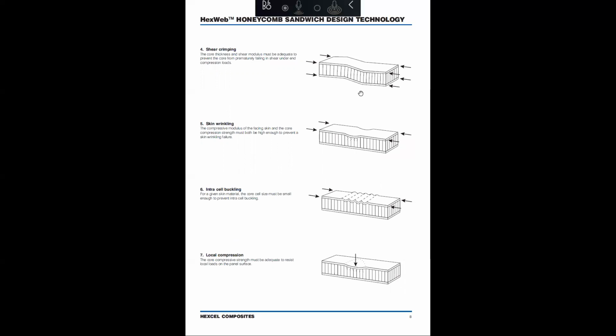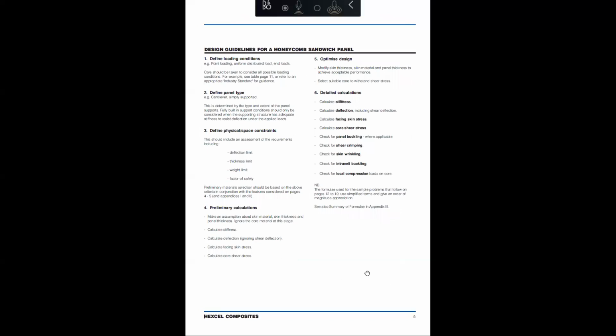That's very important. The skin wrinkling can happen when the compressive modulus of the facing skin and the core compression strength are not high enough. These two, the compression modulus of the face skin and the core compression strength, have to be high enough to prevent this kind of failure mode. We also want the core cell size to be small enough so you don't get intra-cell buckling. You can also have impact events that cause local failure of the core.